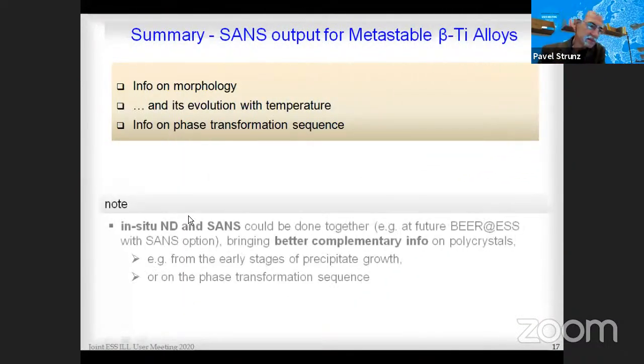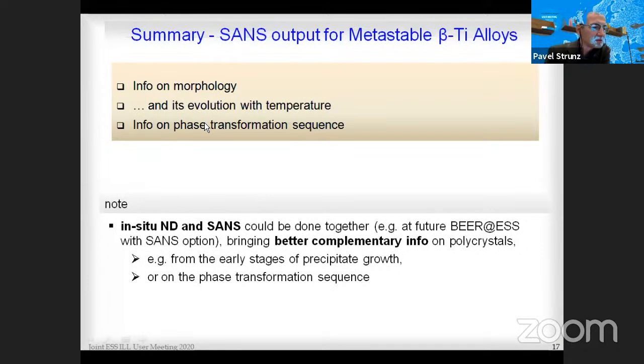Again, there are some sentences about what is the output of this research, but I think that this is a good place to put a note that in situ neutron diffraction and small angle neutron scattering could be done together, which would bring better complementary information on polycrystals. For example, in case we have early stages of precipitation, or we have to find something about phase transformation sequences.